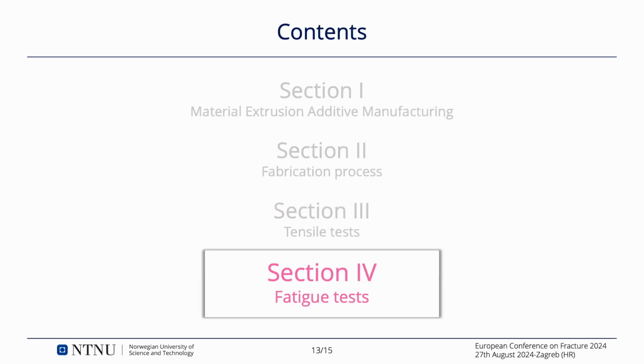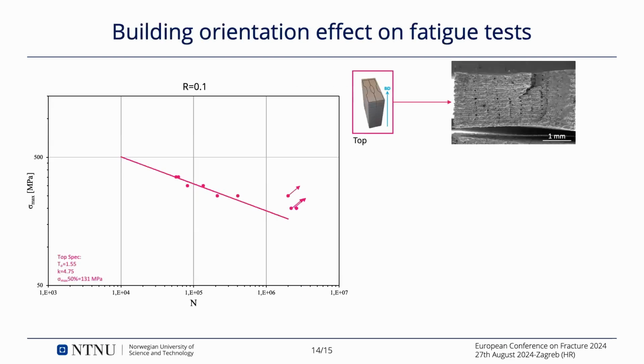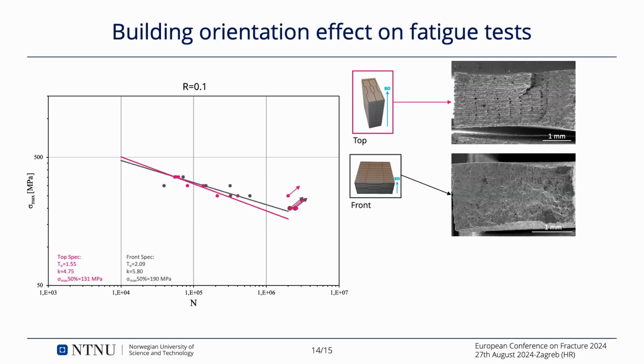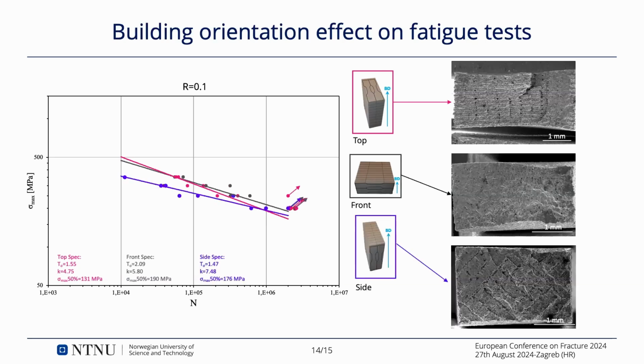Okay, so then we did axial fatigue tests following the same procedure. So here we have the SN curve, load ratio 0.1 for the top specimens, the front specimens, and the side specimens. And what can we say? We can say that strictly speaking about statistical fatigue limit, there isn't a significant difference between building orientations, but the impact of the building orientation is more visible in the area towards the low cycle fatigue area. And this is probably related to the tensile properties that I showed you before. But once again, the difference is more visible in the fracture mechanism.